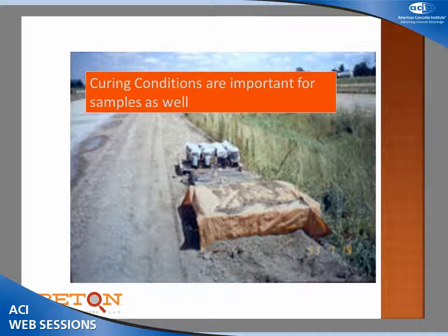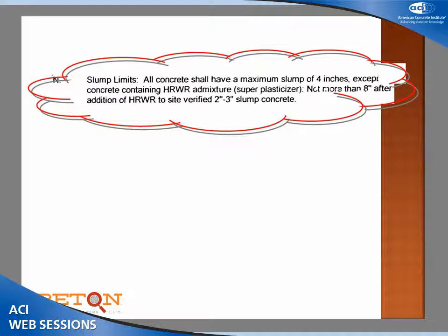Those cylinders are not representative of what's in situ, because they're getting a little bit warm, and the best way, of course, to get them warm is to put them in black molds here. But if you can't do that and you want them to stay warm all night, put some aggregate up there to retain the heat. So we do have some problems, and here's a testing lab I have a great deal of respect for, that could happen to anyone. In fact, it never happened to Semstone because, of course, we never had to report our results to anyone. Then we have a good specification, right?